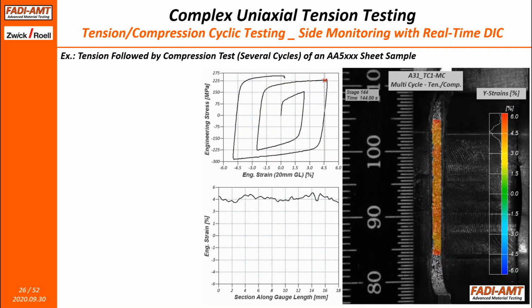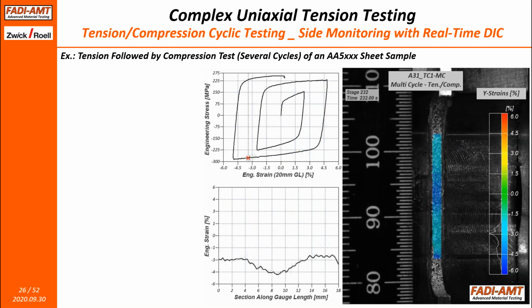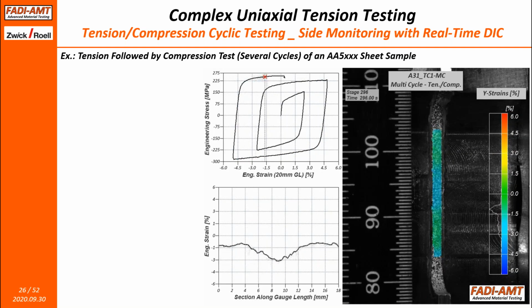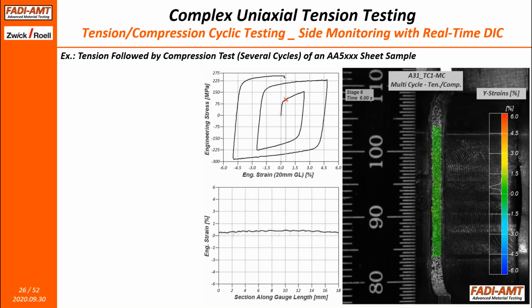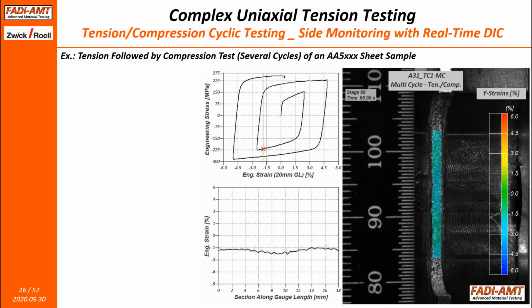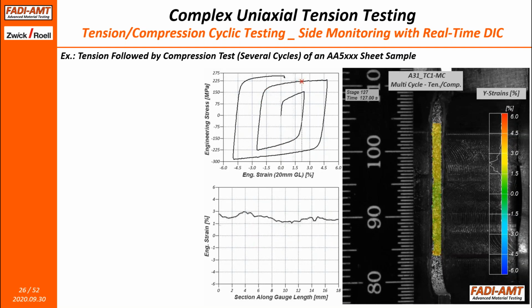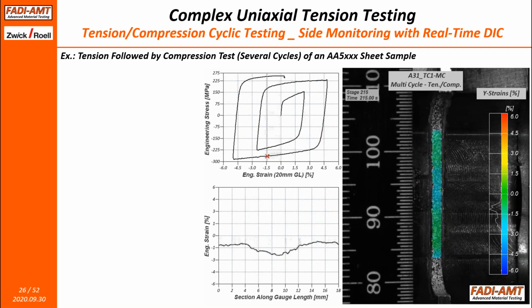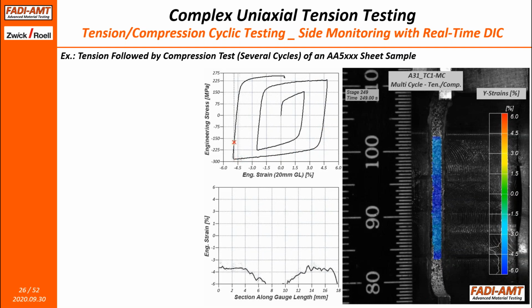This is a video that shows tracking of the deformation from the thickness view of this particular sample. And you can see it basically going up and down in tension and compression. At the same time, at the bottom left, you can see how we monitor the distribution of strains. At the beginning, the material is very uniform, and so there's almost a line strain, but then ultimately, as you can see right now in the video, it's jumpy because the material is entering a banding regime, which is causing this jump in strain.